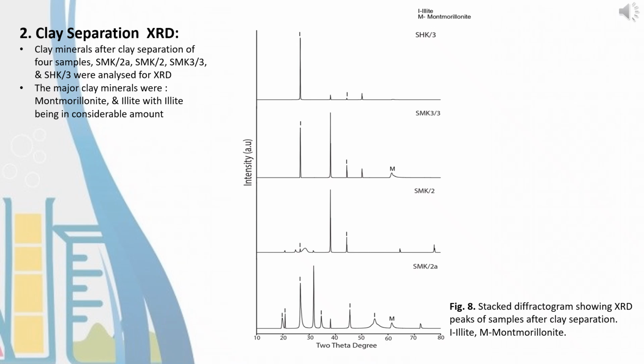Clay separation XRD was performed when it was observed that some peaks still remain unidentified after bulk rock XRD. On performing clay separation on the 4 powdered samples and analyzing the separated sediment particles of nearly 2 to 0.35 micrometers size, it is found that illite is the major clay mineral present in the samples, with some minor montmorillonite. The stacked diffractogram in Figure 8 shows the XRD peaks after clay separation.